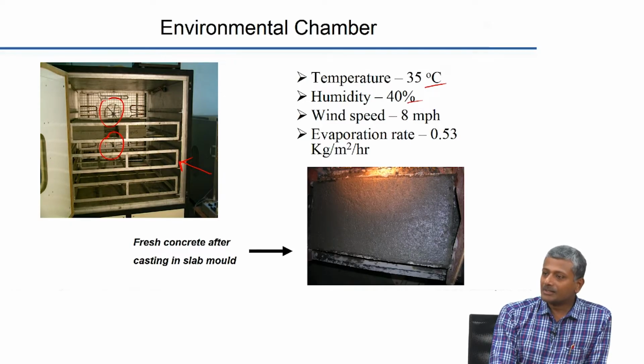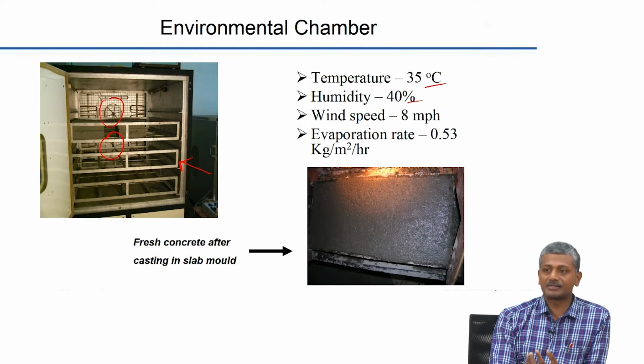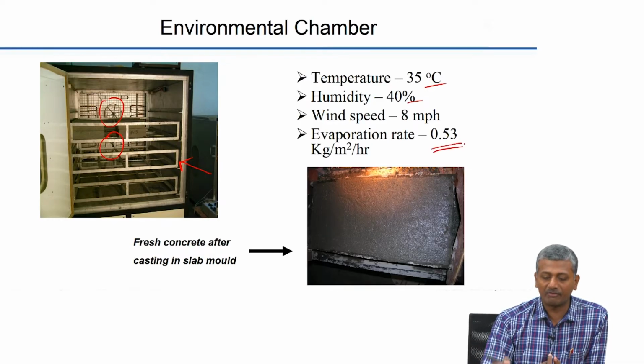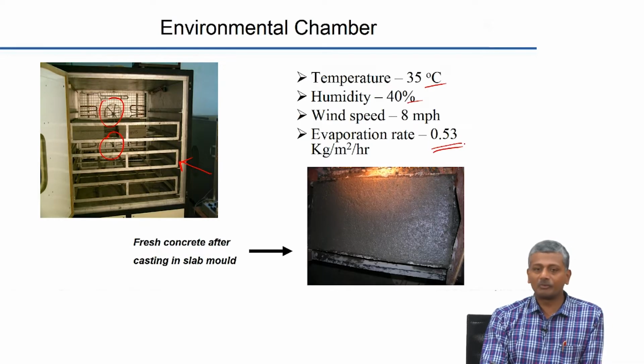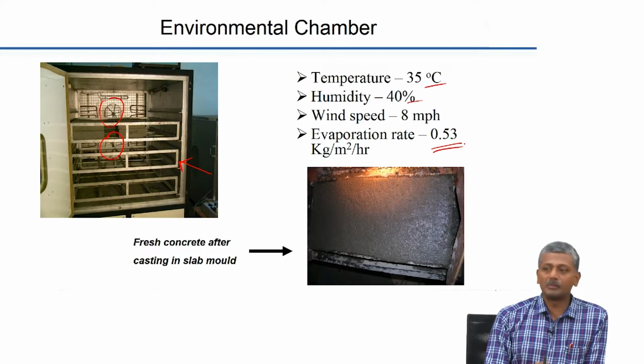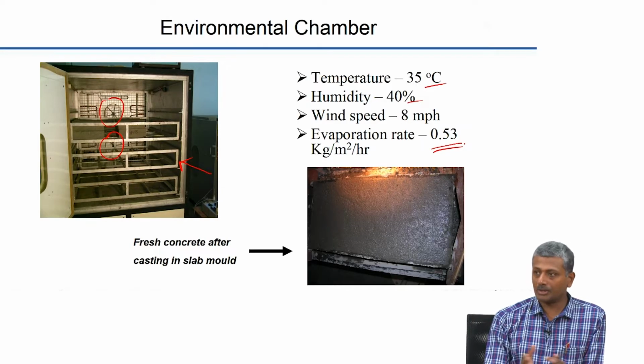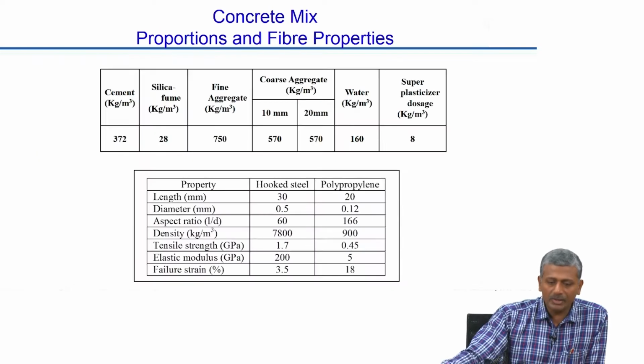But still, this could not really push up the evaporation rate to the critical level, which I discussed yesterday was 1 kilogram per square meter per hour. So here we were able to get only 0.53, but nevertheless we were able to conduct the experiment and demonstrate the differences between regular concrete and fiber reinforced concrete. So let us look at the numbers here.